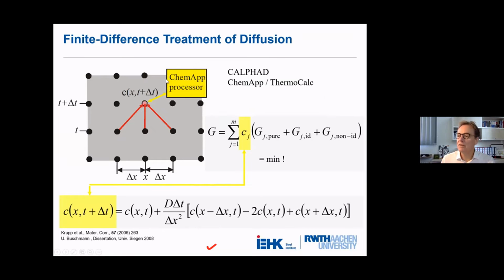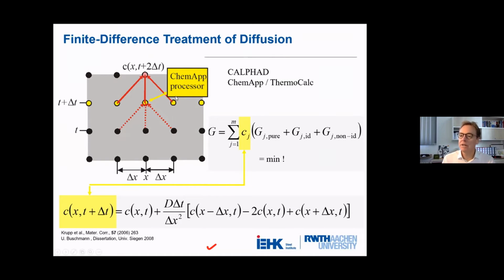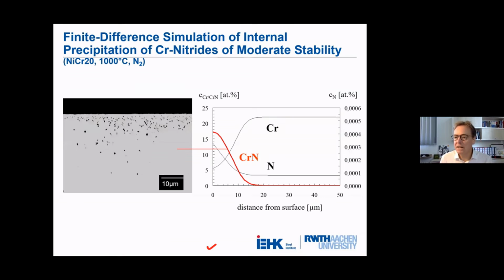We have implemented the CALPHAD approach here using ChemApp. You can also use Thermo-Calc, that is pretty much the same. Then we take this calculated concentration and correct it according to thermodynamic equilibrium. Then we have these new concentrations, and we can calculate the concentration at the next step. That allows us to predict internal corrosion also of precipitates of moderate stability. That is an example of chromium nitride, as you can see here, where we have a diffuse precipitation front.